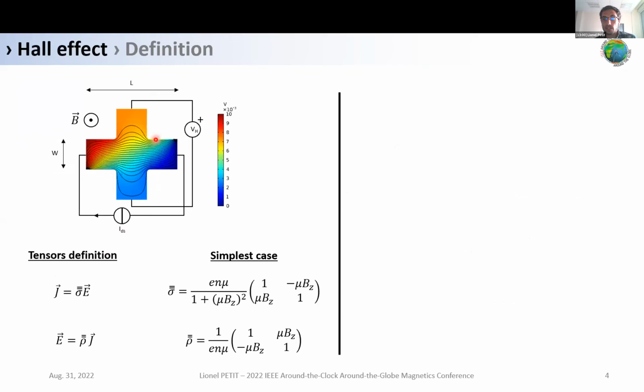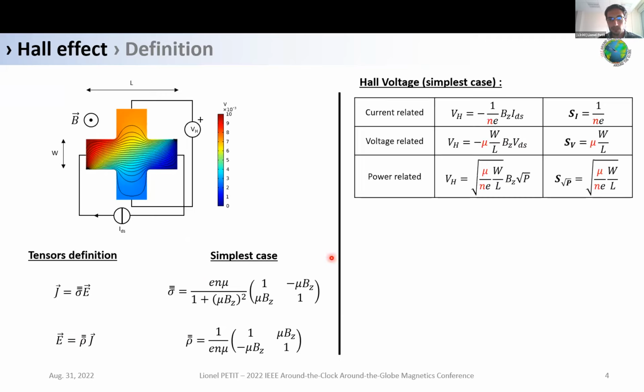The Hall effect is a galvanomagnetic effect that appears when a current flows in a material placed in a magnetic field. And here, because of the Lorentz force, a transverse voltage will develop, which is called the Hall voltage. And in the diffusive regime, which is the most common one, we can define the conductivity and resistivity tensors that take these forms in the simplest case when we only consider one kind of carrier. And from that, we can relate the Hall voltage to the magnetic field and to the bias. The bias can be current, voltage, or power.